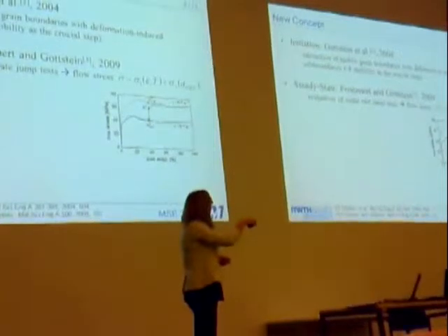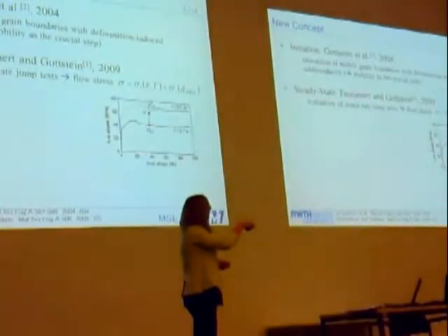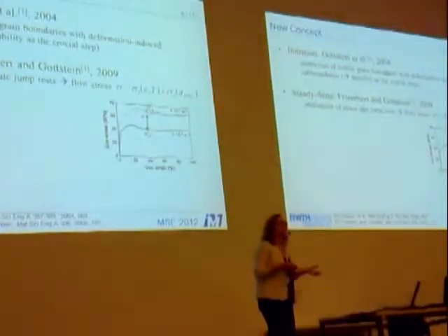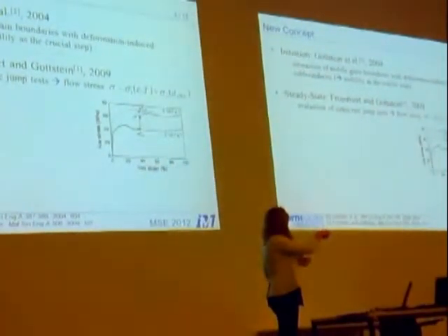The first one is an instantaneous change until the strength of the flow stress here, which is just due to the change of the deformation parameters. And then you have the second part, which is a continuous change to this new steady state. Because there's only left to change the microstructure to these new deformation parameters, this is the important variable that has to be changed. So here we have our grain size sensitivity of the flow stress, and these grain size sensitivities have been evaluated.